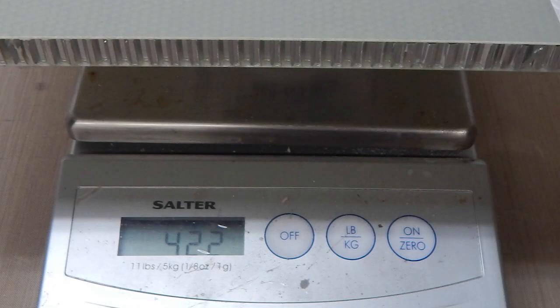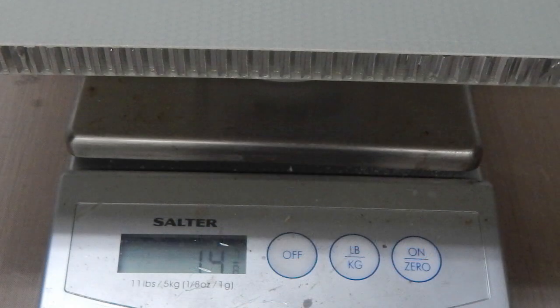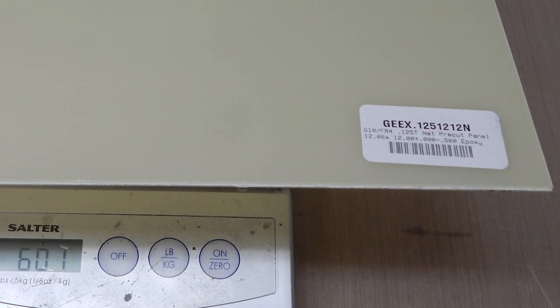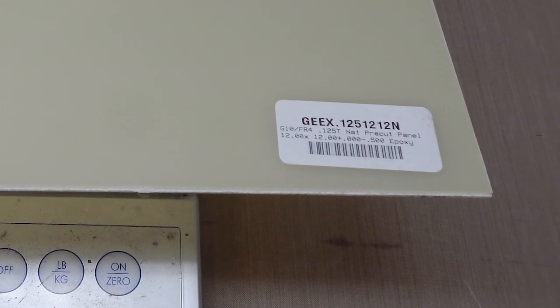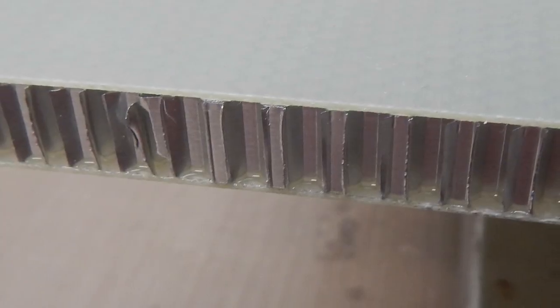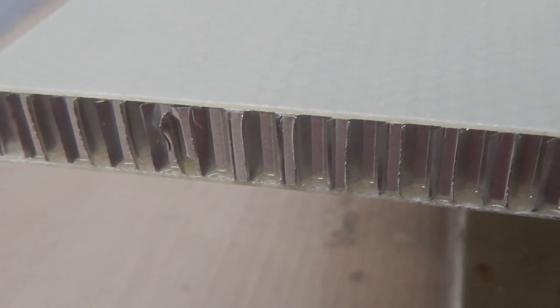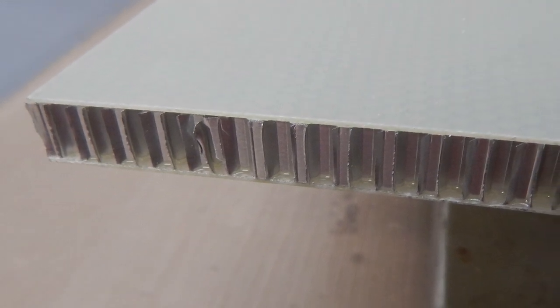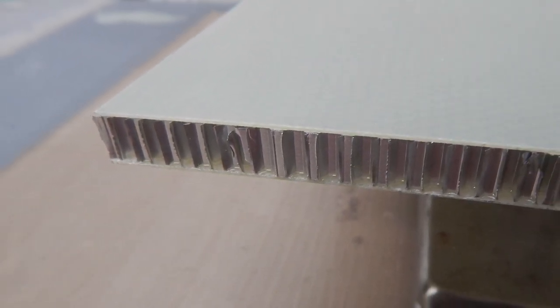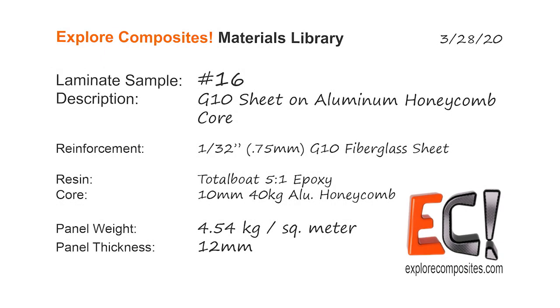I don't have an extra piece to break, but that 1 square foot piece weighed 422 grams, or about 14 7/8 ounces, and comparing that to a piece of 1/8 inch G10, that's substantially lighter and way stiffer. There are the resin fillets formed against the cells of the honeycomb. It's nicely glued on there. And it shows the panel. It's a pretty nice way to build something big and stiff without an awful lot of trouble or fussy material handling. So thanks for checking it out.